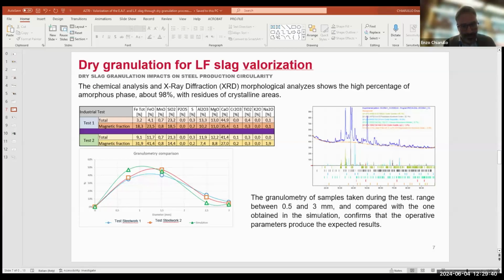And then it's slide number 7. It is related to the result of more relevant result for us. We can see that practically the amount of the composition of the slag was not changing, and even we have a really good comparison between the calculated, the simulation, or let me say the granulation, the grain size calculated by our simulation system and the grain obtained during the process.